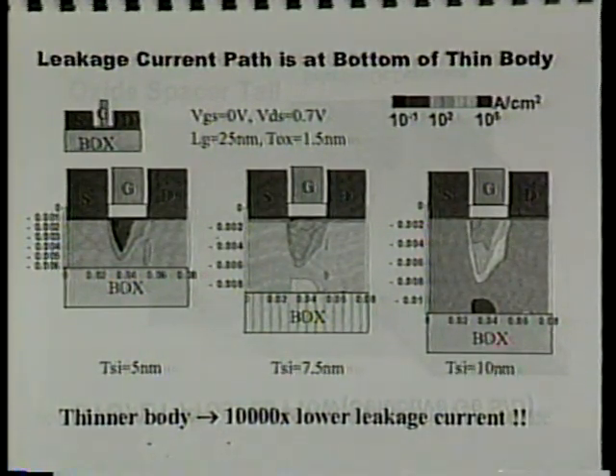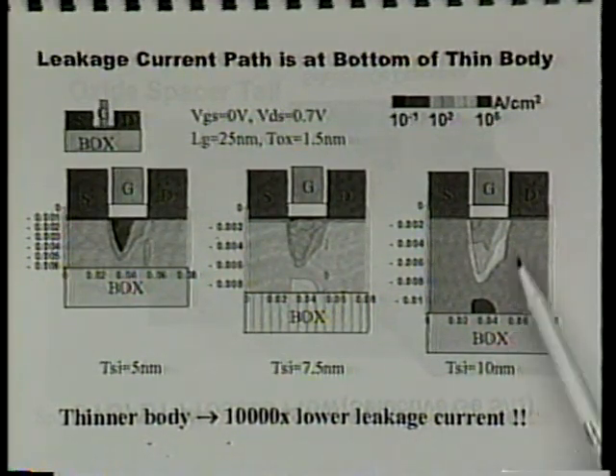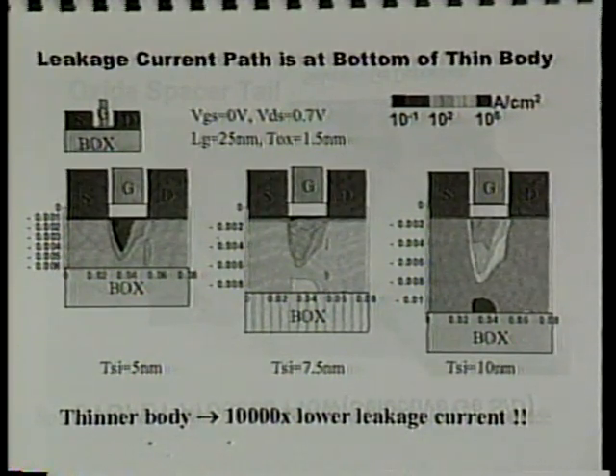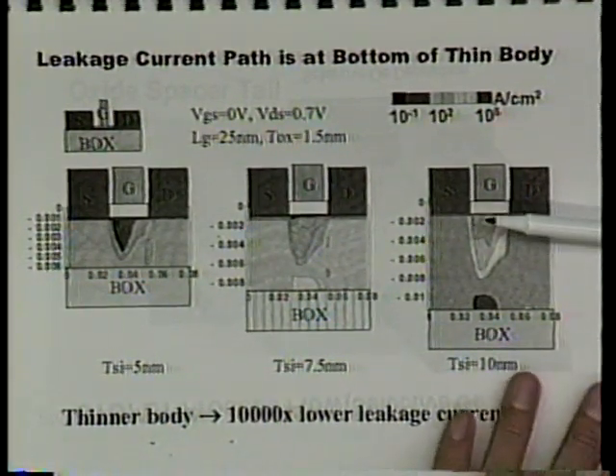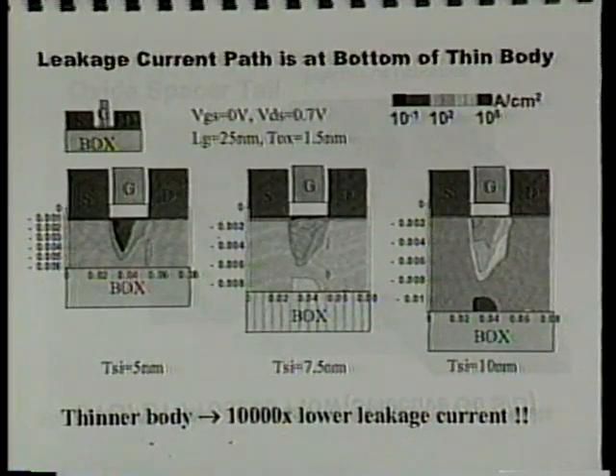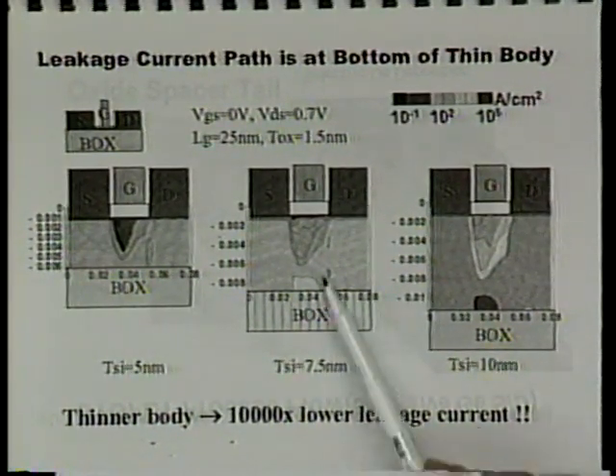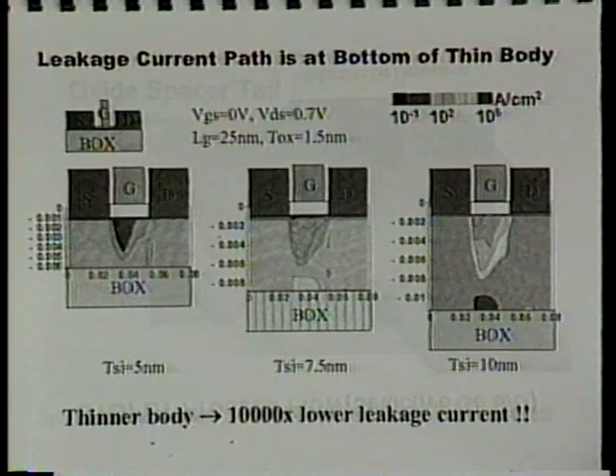If we put 1 volt, it will be even more difficult, of course, even more dramatic, the difference. And what we are doing very simply is start with what most people will consider already a very thin silicon film, 100 angstrom. In fact, most people doing SOI would start probably with 200 angstrom, 300 angstrom, thinking that's the thinnest they want to fuss with. So here's 100 angstrom silicon film. There's 75 angstrom silicon film. There's 50 angstrom silicon film.